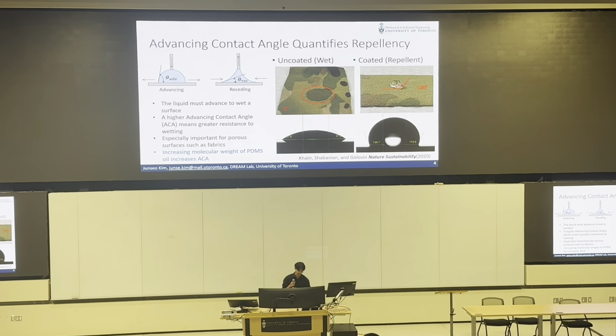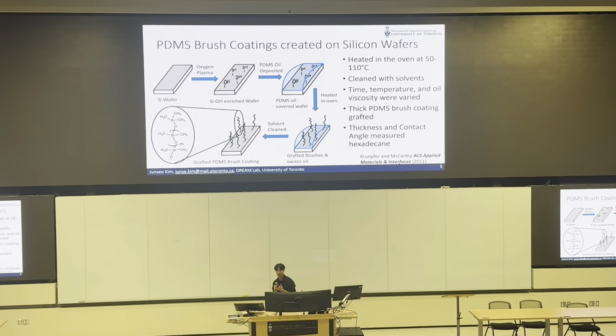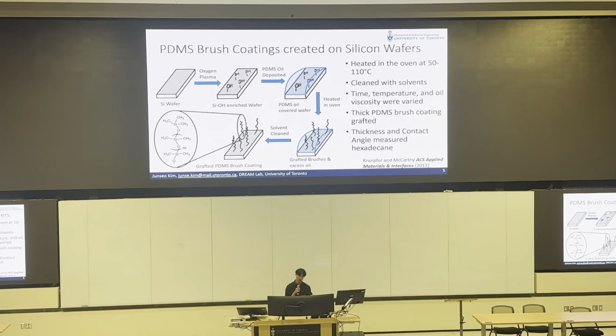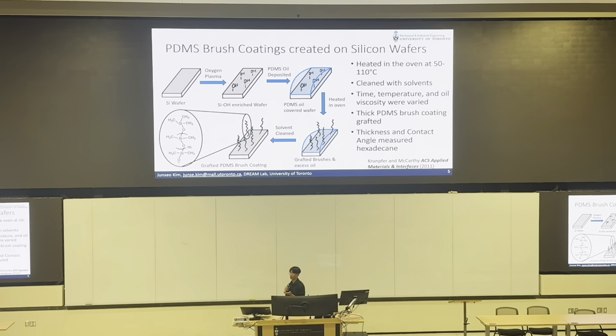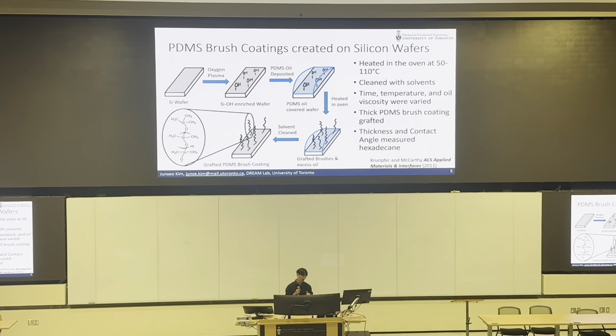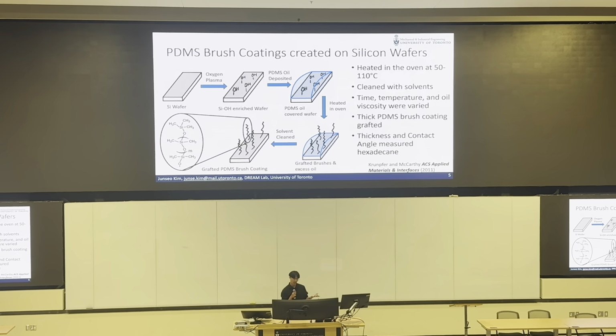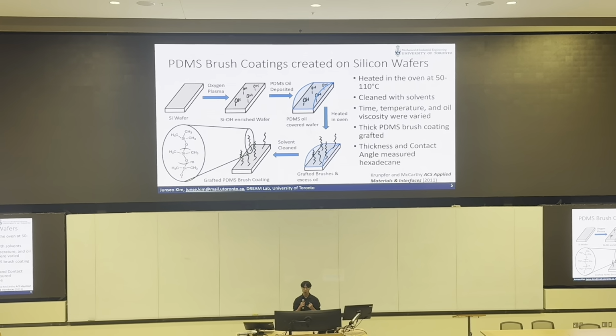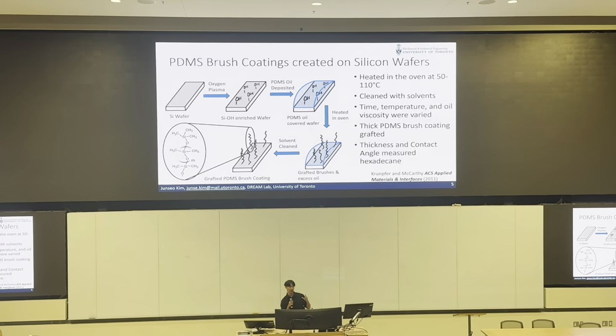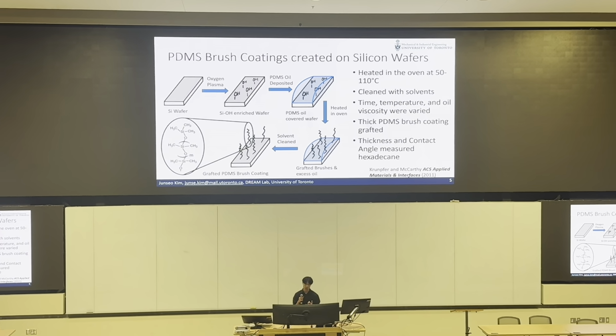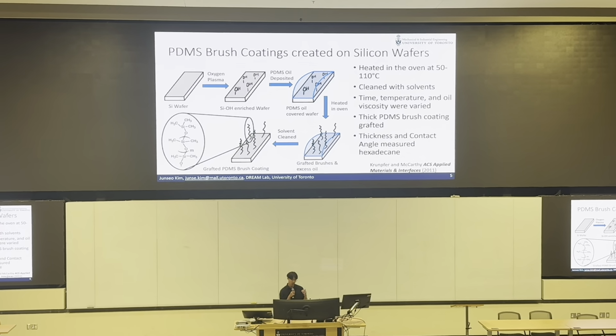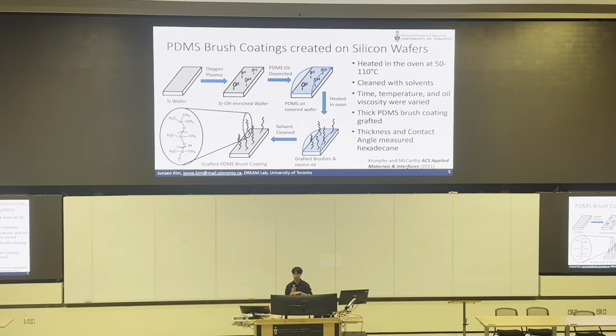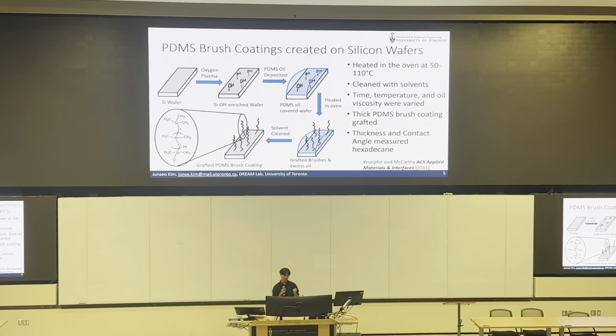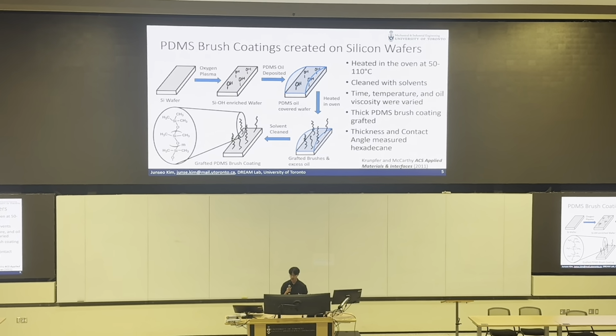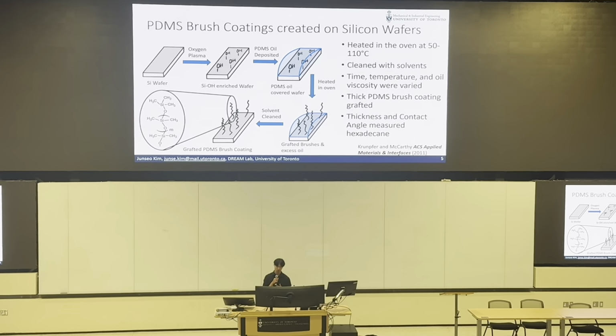And I'll show you the method for how to do that. So PDMS brushes were created on silicon wafers, because they're homogeneous and have a very smooth structure. I take a bare silicon wafer and put it in the oxygen plasma chamber, which creates these reactive silanol SiOH sites. On top of that, I add the PDMS oil of high molecular weight, and then heat that in the oven at whatever temperature, typically around 50 to 110 degrees.